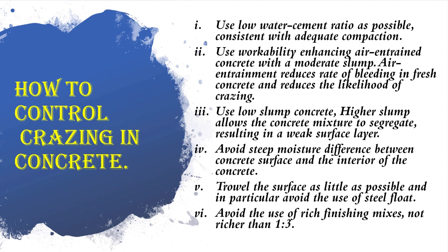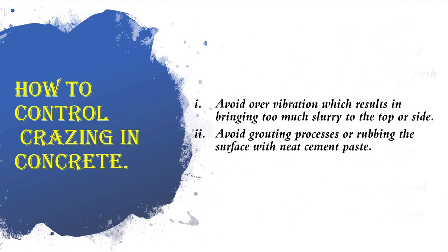Avoid steep moisture differences between the concrete surface and the interior of the concrete. Trowel the surface as little as possible and in particular avoid the use of a steel float. Avoid the use of rich finishing mixes, not richer than 1:3. Avoid over-vibration, which results in bringing too much slurry to the top or sides. Avoid grouting processes or rubbing the surface with neat cement paste.